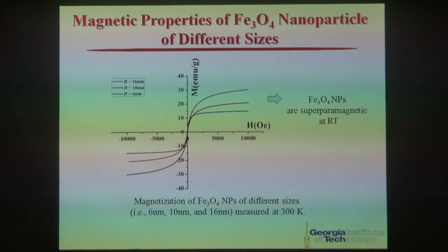Another good example to look at is the magnetic properties measurement for magnetic iron oxide nanoparticles of different sizes we prepared. So here you look at magnetic nanoparticles. So we have 6, 10, 16 nanometers magnetic nanoparticle. So here we don't see the hysteresis loop indicating they are superparamagnetic. So with the increase in particle size, we see the increase in saturation magnetization. So this is also consistent with the report in literature.